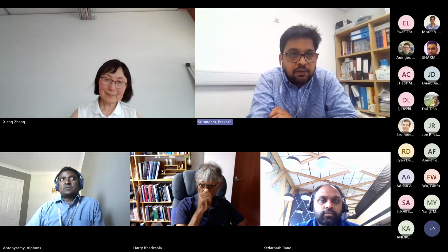Hi, this is Alphonse from GKN Aerospace. Just before asking my question, Professor, with wire arc additive manufacturing and laser metal wire deposition at GKN, we aim at very large parts, for example laser wire deposition of about 6 meters by 3.5 meters. The HIP vessels today are suitable for powder bed, small complex shapes, about 500 by 500. I also explored the biggest HIP vessel in the world, about 3.2 meters wide and 1.5 to 2 meters tall. For large titanium aerostructures, HIP as a solution doesn't work out in a practical way.